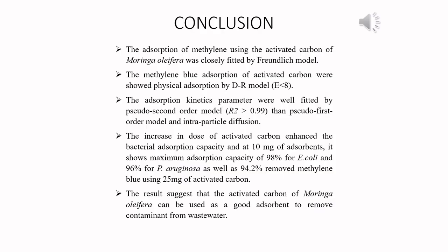I would like to discuss the conclusion. The adsorption of methylene blue using the activated carbon of Moringa oleifera was closely fitted by the Freundlich model. The methylene blue adsorption of activated carbon showed physical adsorption by the DR model. The adsorption kinetics parameters were well fitted by the pseudo second order model, then the pseudo first order model, and intraparticle diffusion.